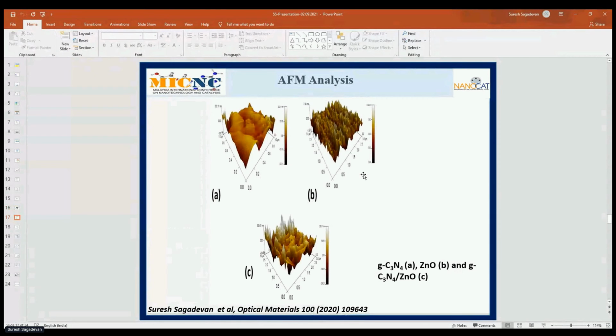So next we performed AFM analysis, atomic force microscopy imaging. You can see the three samples here: A is graphitic carbon nitride, B is zinc oxide, and C is the composite sample. From this analysis, once again we can confirm that graphitic carbon nitride has a sheet-like structure. The first image shows a sheet-like topography, which matches well with the TEM image. Similarly, in the topographic image of zinc oxide, you can see the rod-like structure in 3D view. The zinc oxide samples are also arranged in a rod-like manner.